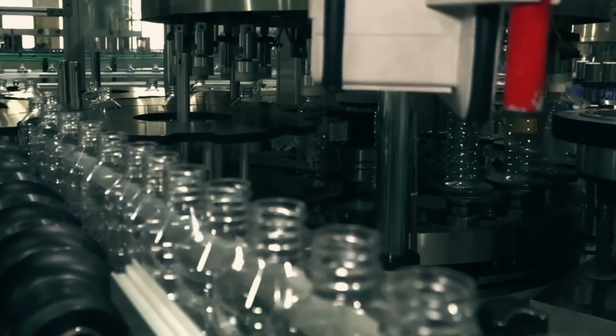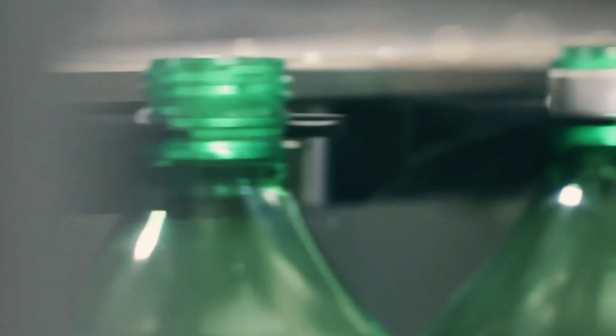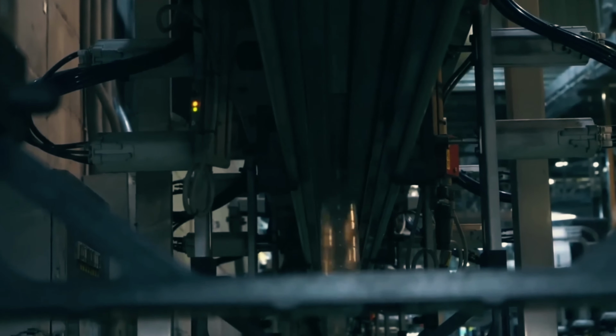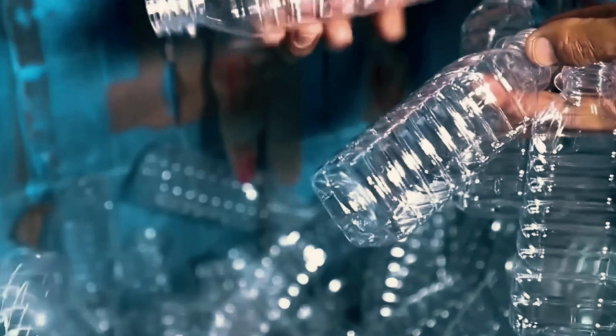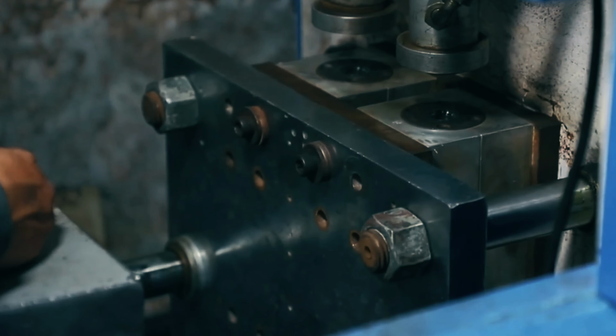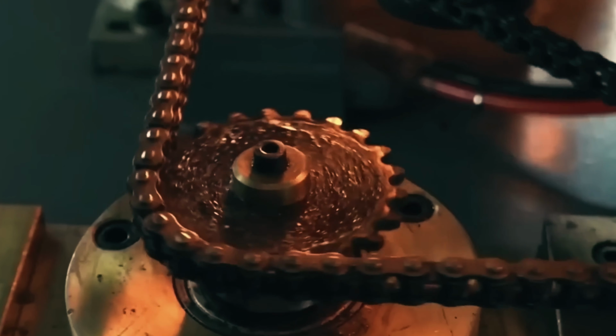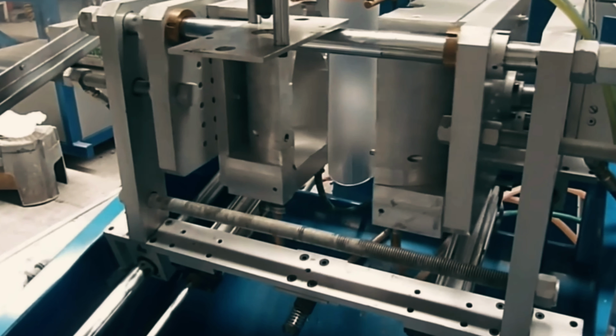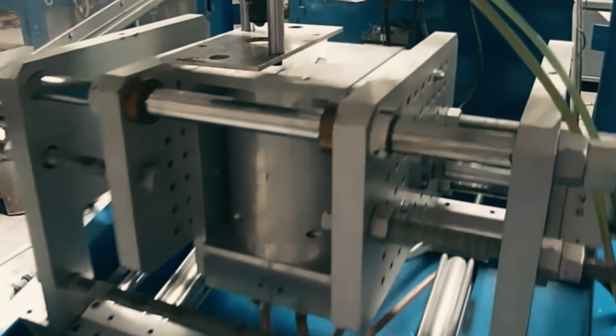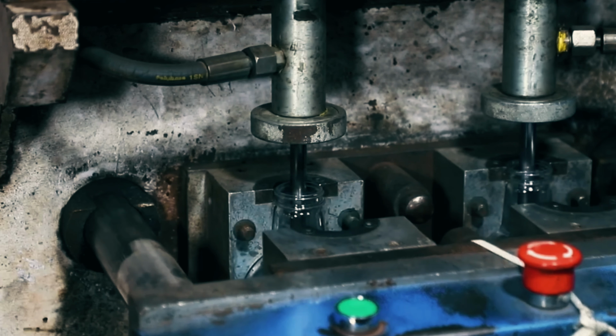The bottles are cooled instantly, trimmed of excess plastic, inspected by high-speed cameras for any defect invisible to the human eye, and sent down the line to be filled and capped, sometimes at rates exceeding 1,000 bottles per minute. Here's the part most people miss. That blow molding step happens so fast and under such tightly controlled pressure that a single degree of temperature difference can cause a bottle to warp or burst on the line.